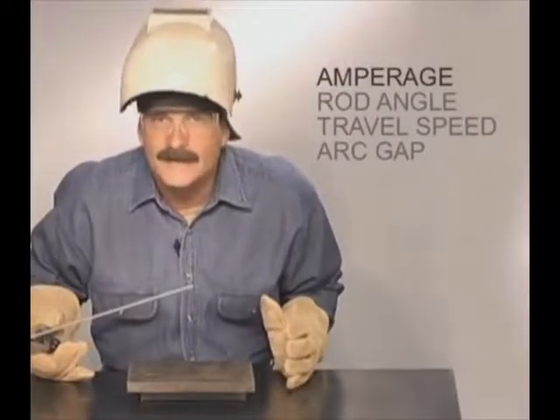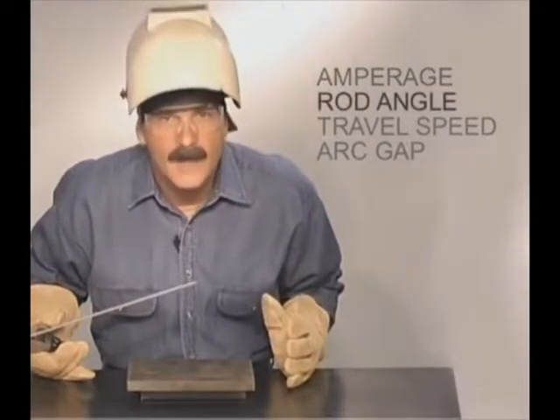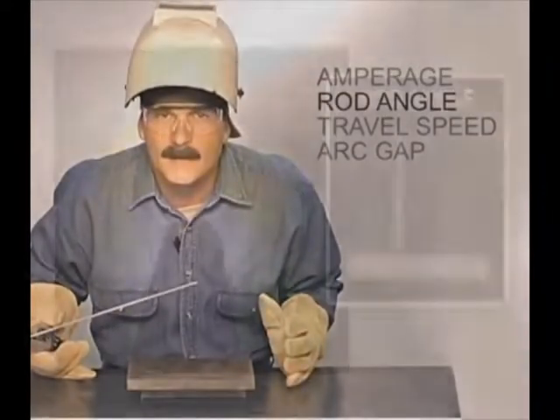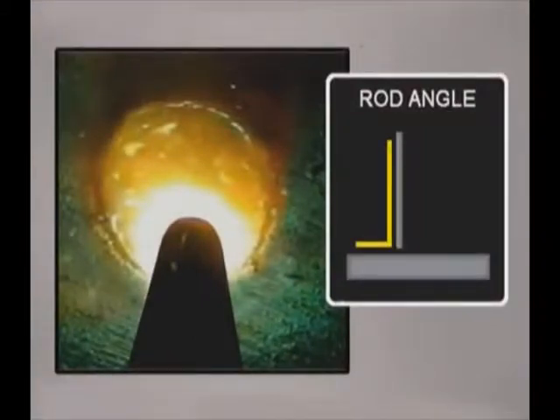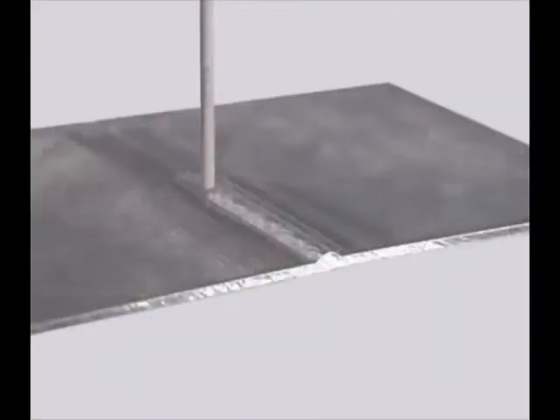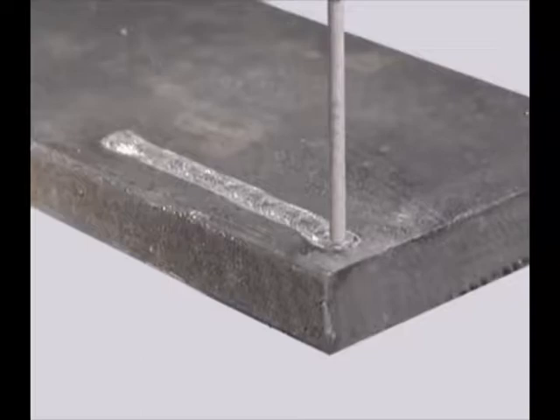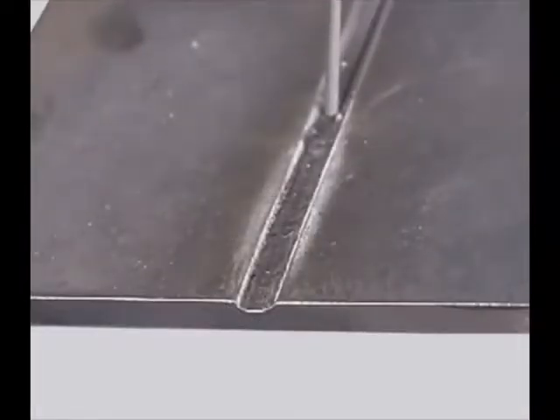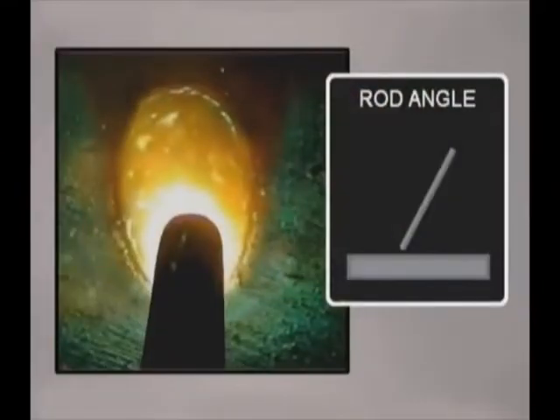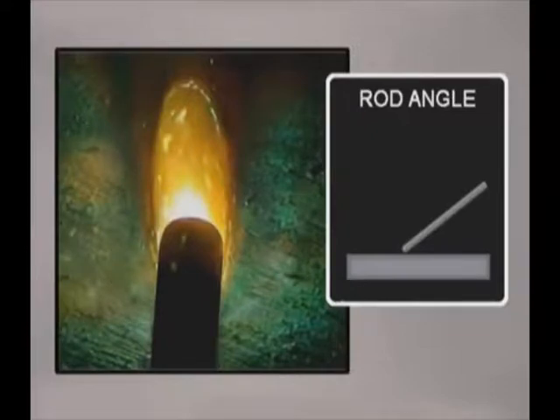Regardless of which rod you use, the amperage only provides the heat. The rod angle determines how fast the metal will heat up. When the rod is held more perpendicular, the molten pool forms and spreads quickly, allowing a faster travel speed to limit penetration on thinner metals, deposit less metal for a smaller weld, or flatten the bead in a bevel. As the rod is angled, some of the heat is taken off the metal. A slower travel speed can be used to build up a crowned weld bead. If the rod is angled too much, the metal won't get hot enough. The molten pool will narrow, the bead will stack up, and you'll lose control of the edges of the puddle.